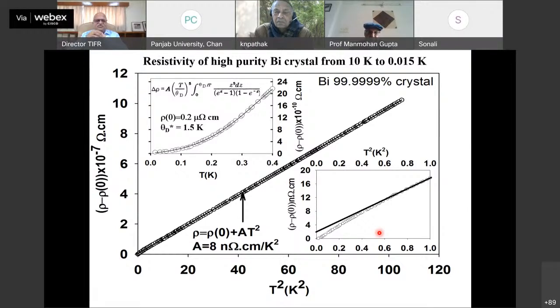This is done with the dilution fridge, so you can measure using SQUIDs, and you see that the normal properties itself are changing at something like 0.6 Kelvin. See, initially it shows the T-square dependence, and then it deviates strongly here. You see it at something like 0.6 K. So something happens to the normal properties of bismuth at 600 millikelvin. And that is the reason why it is superconducting at low temperature. Only theories can tell. Of course, theorists want us to measure down to the lowest temperature, which is what we are trying to do.